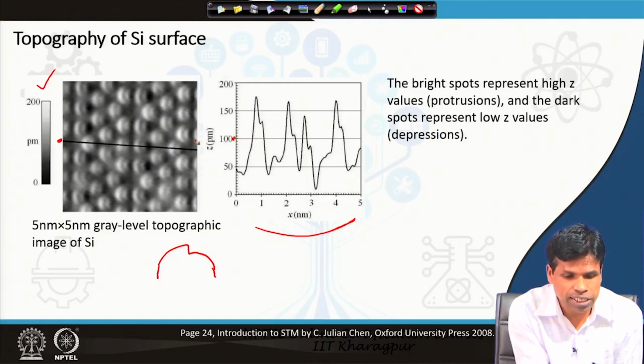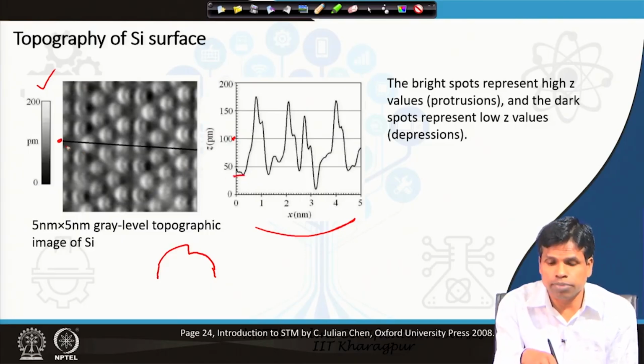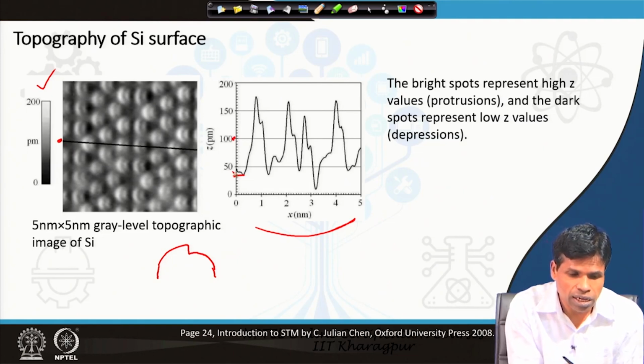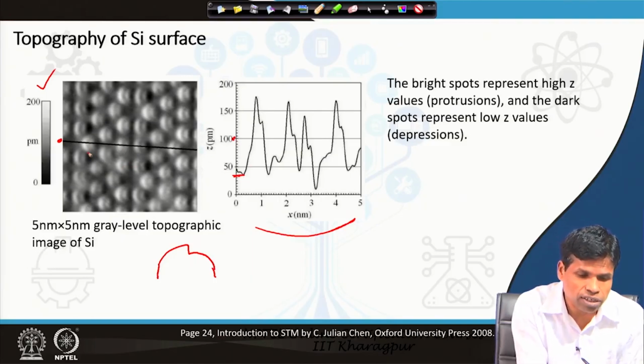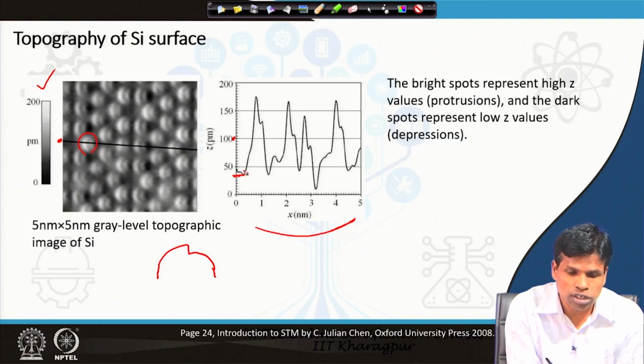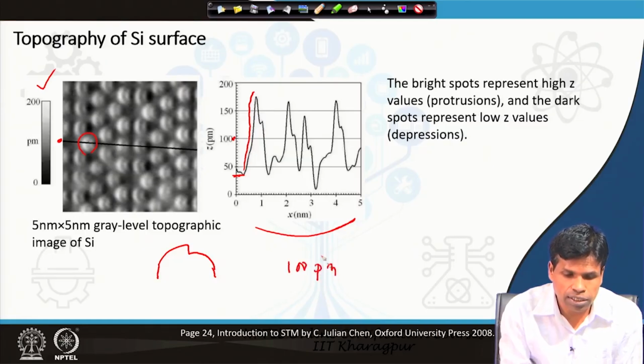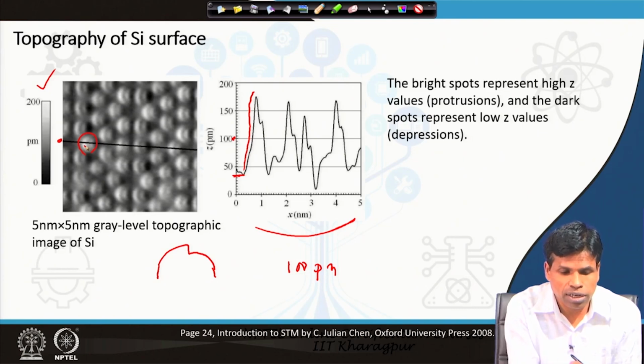This region looks darker, that means the height is low, it is in a depression, and that would measure a small current. This is almost around 70 picometer downwards, and then as soon as a brighter portion comes, which is an upward portion or protrusion, the tip has to go upward, and it has gone upward by around 50 to 150, a height of around 100 picometer. The height of this sphere is 100 picometer above the ground level, and then it has come down.